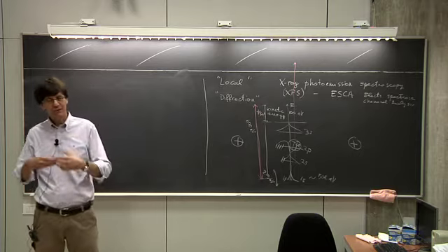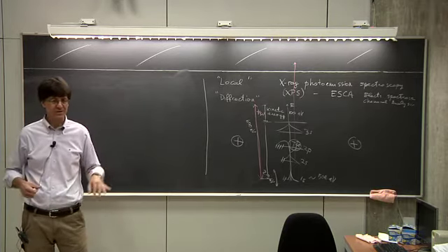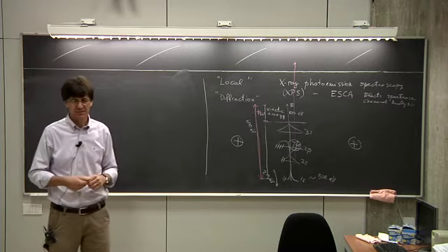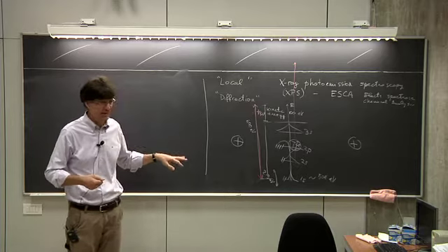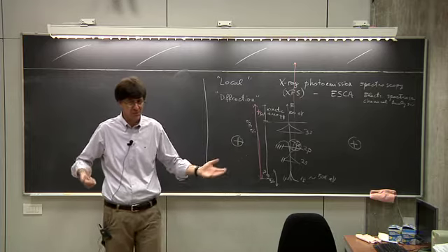And from that, suppose you find 12, for example, then you know that it's not BCC, it's not simple cubic. It must be FCC, HCP, or some other structure. If it is a crystal, that you will never be able to tell based on these experiments, it might be an amorphous system, you don't know.